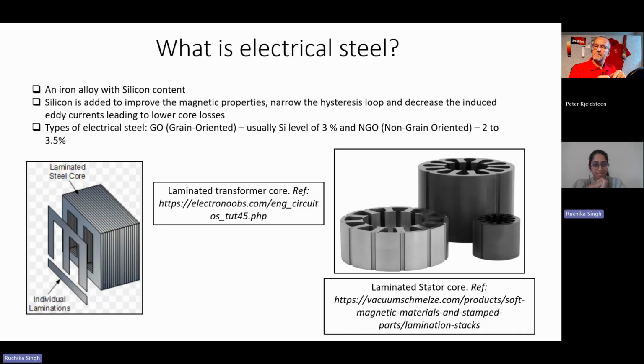When you talk about packing these sheets into a stack, there's something called stacking factor, and you want that to be high. So if you want to have a rotor core of, I don't know, 10 millimeters, and maybe I need 30 sheets, for example, to get that, now that 30 sheets, you need to calculate taking into consideration the thickness of the electrical steel. Now, the thinner the steel, the higher the number of sheets you need to have to get that size and a higher packing factor. So I think you need to have a higher number of sheets if you have a thinner material to get the stacking factor required for that core for a given core size. So that is definitely a very important factor to consider when we talk about the saturation level.